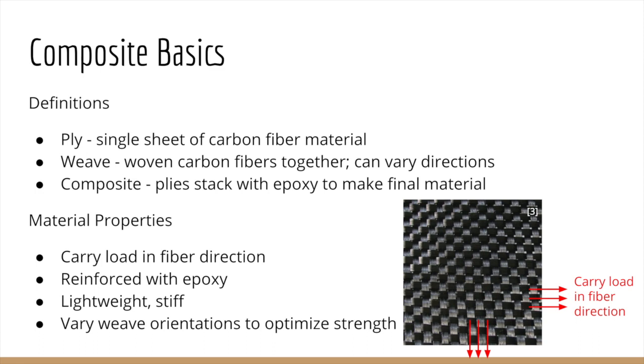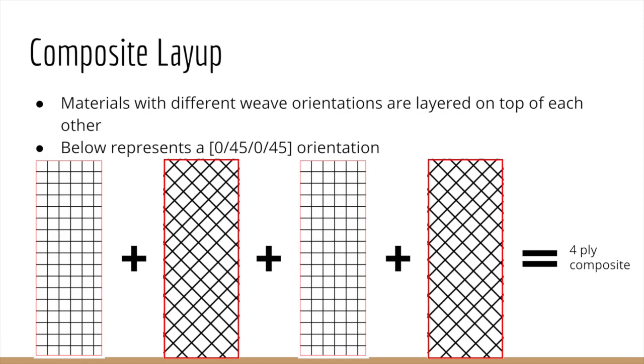Carbon fiber is lightweight, stiff, and you can vary the weave directions to optimize the strength, and that's what this project focuses on. For a carbon fiber layup, we are going to take different plies, like I mentioned before. So we have the 0-90 orientation, and then we can lay a 45 orientation, then a 0-90, and then a 45 on top of each other, and that's a 4-ply composite. Varying those weaves is what I look into for the rest of this project, and what I'll be going into in more detail.